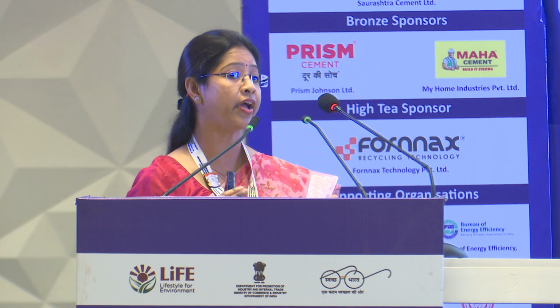So that was the conclusion, that mineral carbonation through dry route does not show any carbonation reaction, and however we have obtained positive result in case of wet route, in case of both LD and FGD gypsum, and we have found that the mineral composition or the phases which are present play a very important role towards mineral carbonation reaction. And we can say that steel slag, FGD gypsum and phosphogypsum show potential for mineral carbonation in reduction of CO2 footprint.